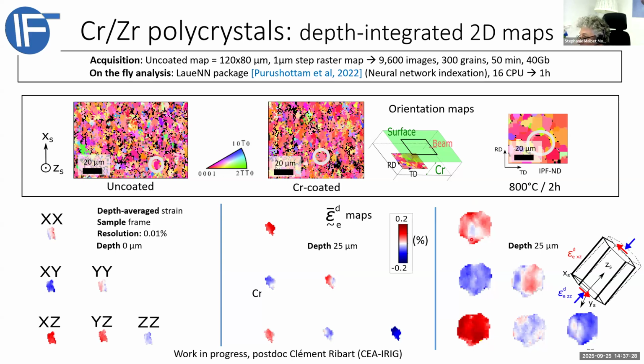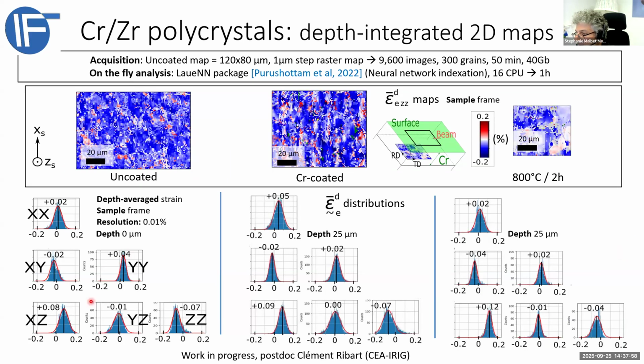This is a grain where the c-axis is more or less pointing normal to the surface. And then how can we interpret the main color of these different lattice parameters or strain components? We can interpret that by a compression along the c-axis, and a shear component, which is parallel to the rolling axis during the manufacturing. And thanks to this Laue microscopy, you have all the components for all the points.